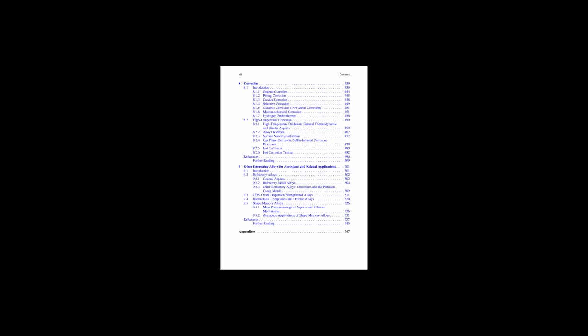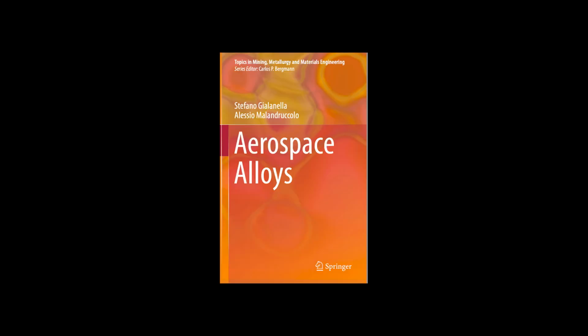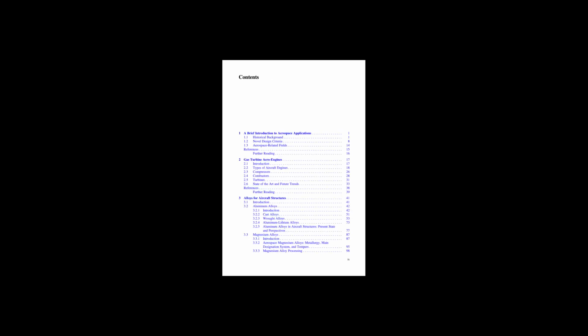They usually remelt it 2 or 3 times. Right, for maximum purity and consistency. Exactly. There are other melting methods too, like electron beam, cold hearth remelting, EBCHR, but VAR is very common. And then shaping it. Forging. Forging is the most common way to shape titanium parts. Hammering or pressing the ingot into the desired shape, usually at elevated temperatures. You can forge it in the alpha-beta temperature range, or for some alloys entirely in the beta range, although beta forging needs really tight process control.